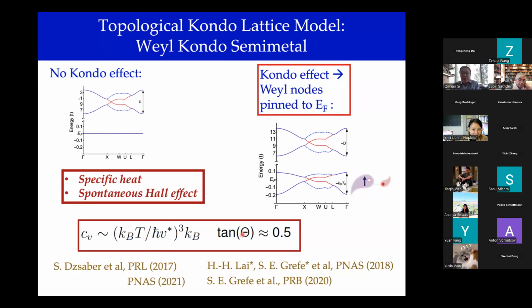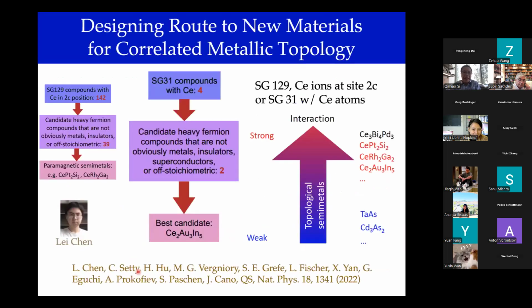And in addition, the Berry curvature induced Hall effect turns out also to be extremely large, as characterized by the Hall angle of the order of a gigantic number like 0.5, and that's in fact what's seen in these semi-metallic heavy fermions as well. So this is a heavy, highly renormalized Fermi liquid with a twist, through the cooperation of lattice symmetry and electron correlation in the form of the Kondo effect. And this cooperation can be taken advantage of.